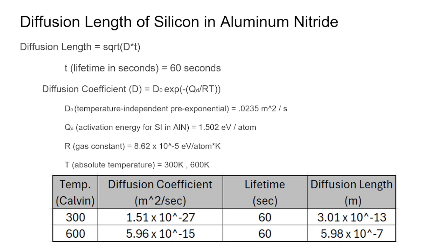And at a temperature of 600 Kelvin, you would get a diffusion coefficient of 5.96 times 10 to the negative 15 meters squared per second. Lifetime 60 seconds again. Plugging both of those two values into the diffusion length formula, you would get a length of 5.98 times 10 to the negative 7 meters.